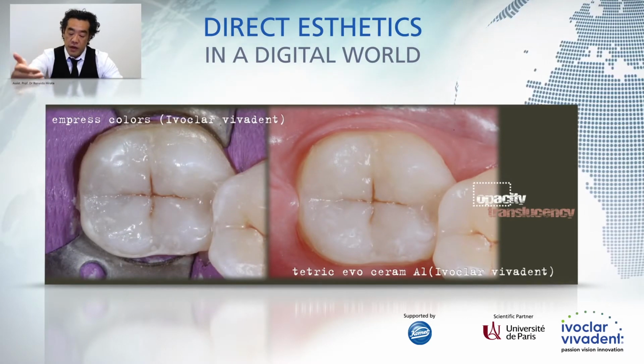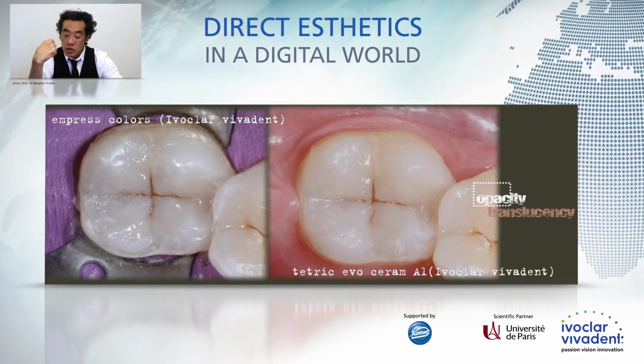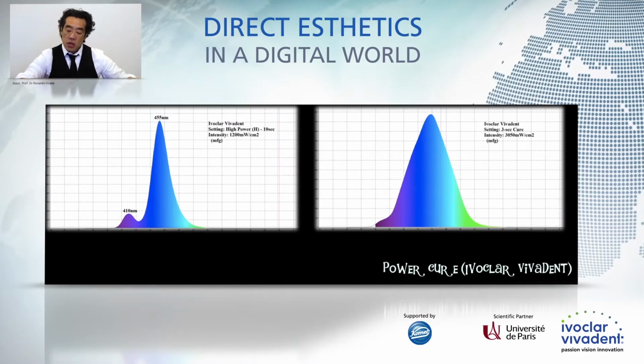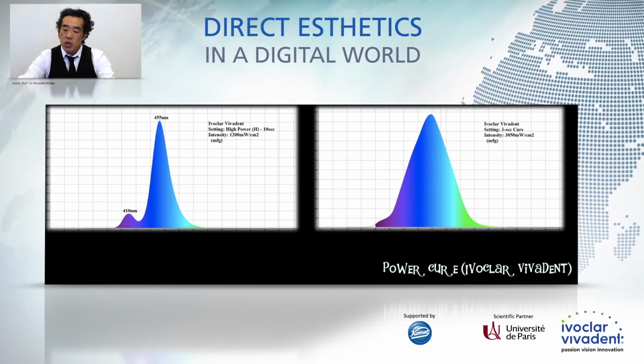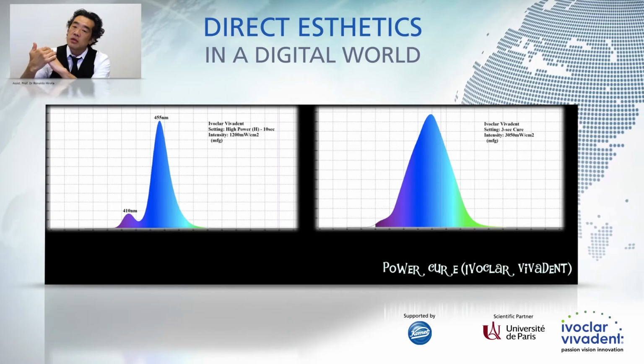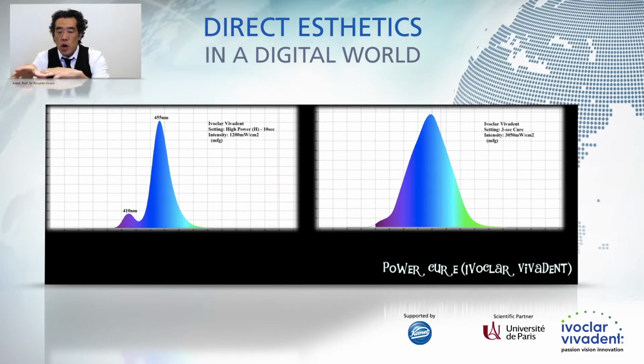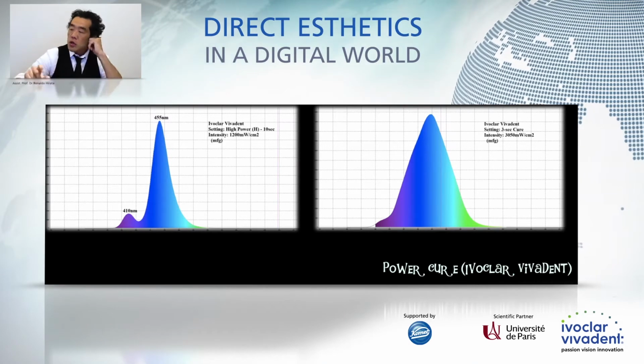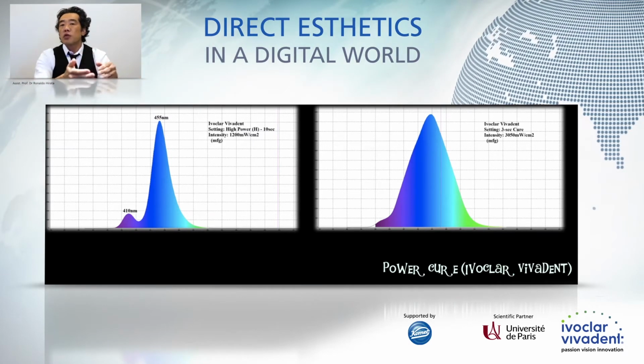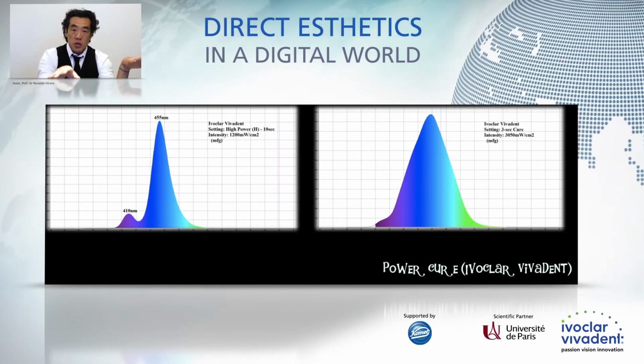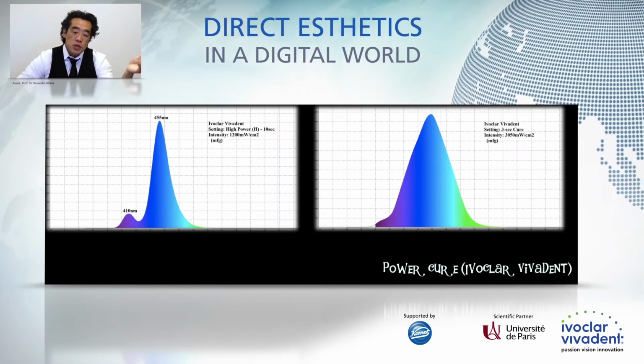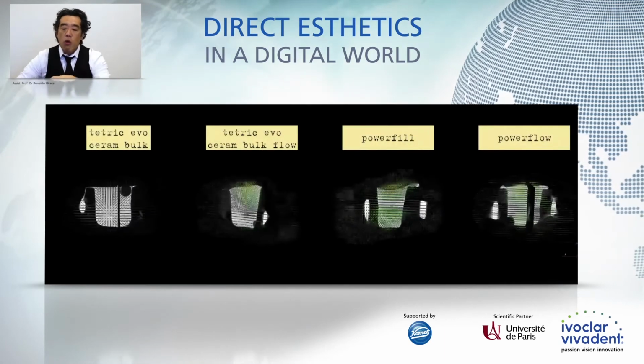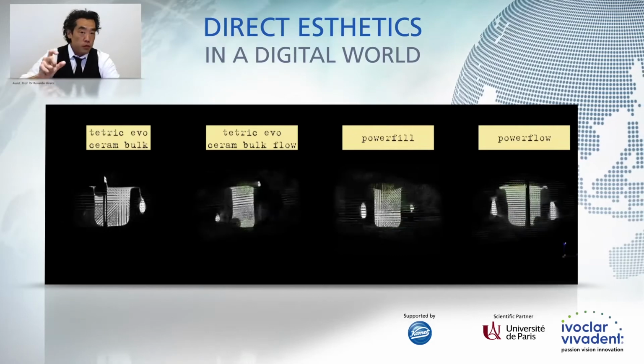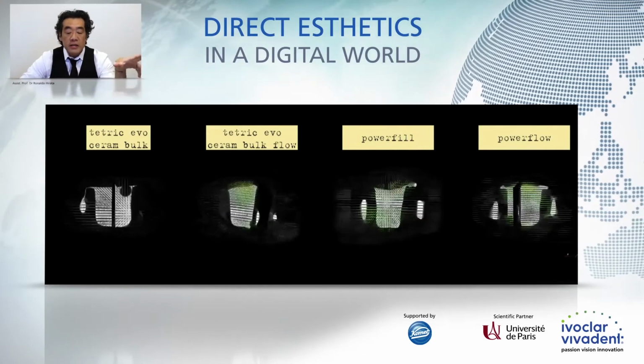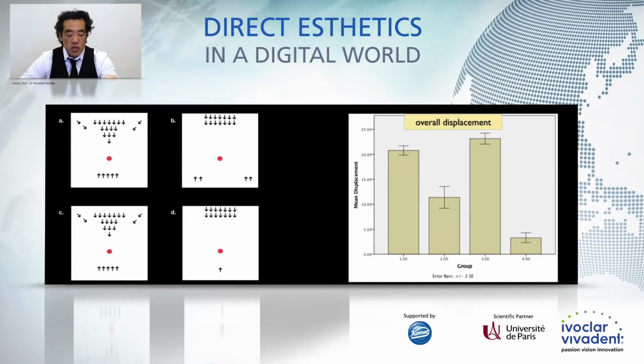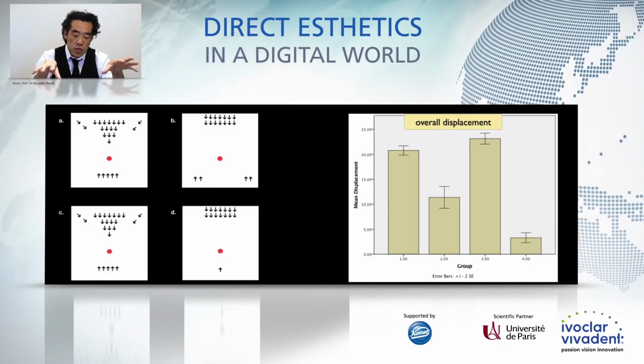What we're going to discuss in this 1 hour lecture is that we also have some bulk fill composites that can be used with high intensity curing lights, 3000 milliwatt per square centimeter. You can cure up to 4 millimeter, but instead of curing for 20 seconds, which is the average, you just use 3 seconds. I did some research about that. These newer composites we call power flow and power fill. They are bulk fill composites to be used with these high intensity curing lights. This is a good result that we have as well with these newer composites.